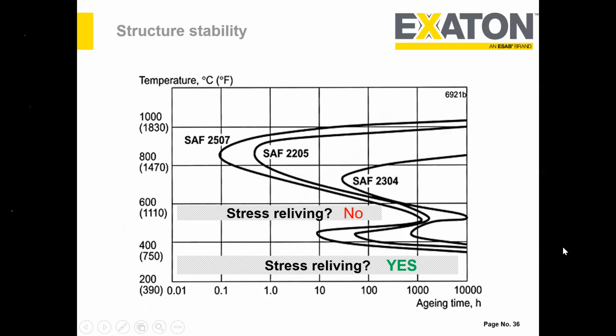Okay, so this is an important slide. Sometimes we get a question: can we go for a post weld heat treatment? We have carbon steel clad with duplex or super duplex. So can you do stress relieving? Try to avoid stress relieving, and if it's really required, definitely it is not at all recommended at 600 degrees centigrade. You see this one, it can intersect the C curves or even the high potential of 475-degree embrittlement. Anything above that is absolutely not recommended.